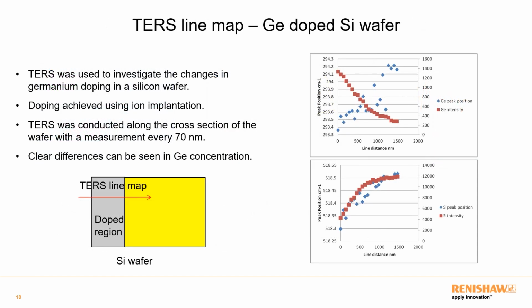My next example is carrying out tip-enhanced Raman spectroscopy on a semiconductor wafer. This is a silicon wafer which has been doped with germanium, and the wafer was ion implanted from the top. So the top, say, 100 nanometers of the wafer has differing levels of germanium in it, and we want to do TERS to try and identify what that germanium concentration is. Here we're running on a cross section of the wafer, and we were able to plot the germanium peak position and germanium intensity against line distance.